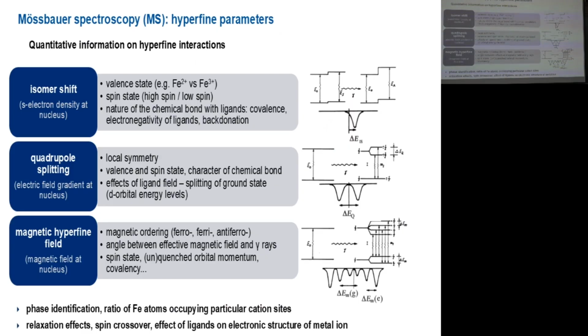I think I should skip certain details, but just briefly, the analysis of Mössbauer spectra provides the set of hyperfine interactions, the set of hyperfine parameters. And there are 3 hyperfine parameters: isomer shift, quadrupole splitting, magnetic hyperfine field, and all these parameters provide some useful information. But the main message regarding Mössbauer spectroscopy is that it really enables to quantify different forms of iron, different oxidation states. It enables to distinguish them in different sublattices and quantify them. And you can collect also some information on, for example, spin state of the iron, if it is low spin, high spin, and so on.